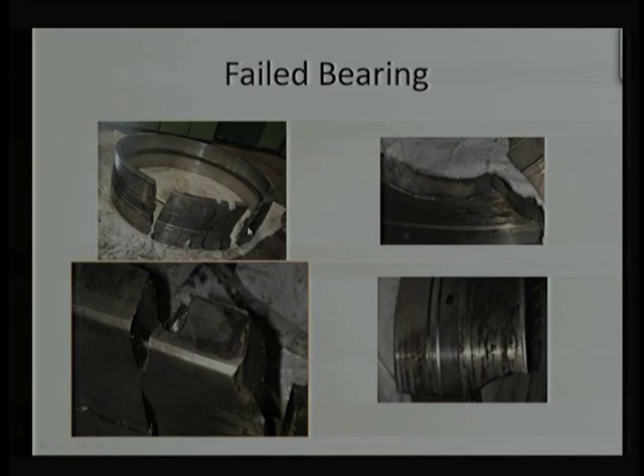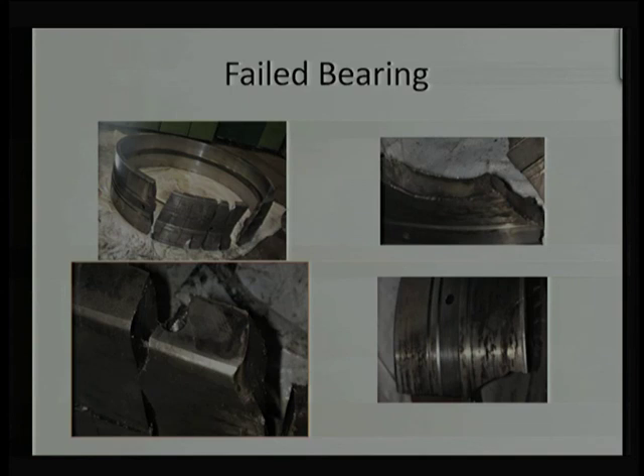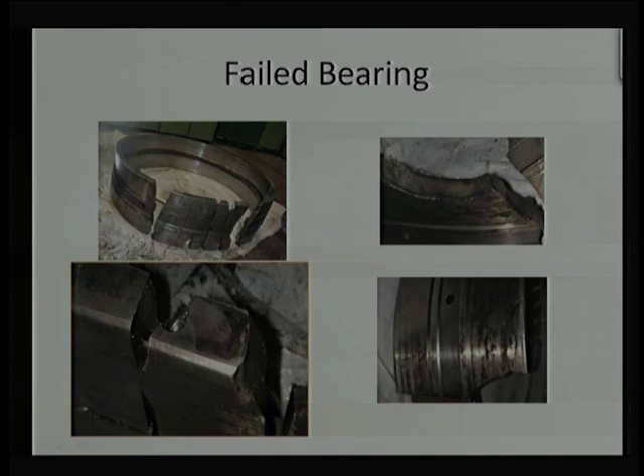These are the figures of the failed bearing. You can see the outer ring, which failed and broke into multiple pieces with deep cracks running from one end to the other — almost like cutting fruit with a knife. Interestingly, failure occurred in only one quarter of the ring; the remaining three quarters remained as a single piece. On magnification, we can see corrosion marks, indicating water or an acidic environment played an important role.